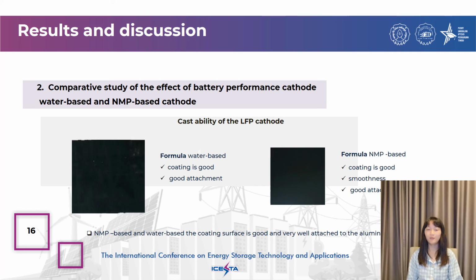Continuing with the comparative study, I noticed the mixing time varied greatly between the water-based slurry and the NMP-based slurry, with NMP-based mixing much quicker. I also found that the cathode surface coatings of water-based and NMP-based have slightly different surface characteristics. Both water-based and NMP-based mixtures have good adhesion and smoothness, but the NMP-based mixture has a slightly smoother appearance.